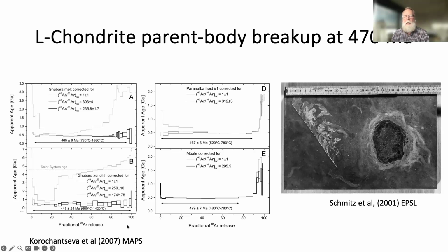Korochantseva et al. worked on some correction techniques to account for excess argon and really got some very nice results for a variety of chondrites. And you can really see very clear plateaus. This one is Ghubara here, and then this is another one, Paranaiba and Mbale, and I'm going to talk about Mbale. They all have very well-defined impact ages of around 470 million years. I mean, really nice plateaus. You'll notice something else, though. There is an older age at high temperature release. At the end of the release, we're getting some older ages, and I'll talk about that in a minute.